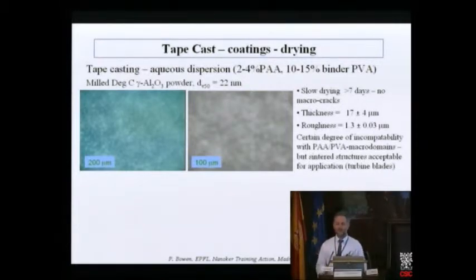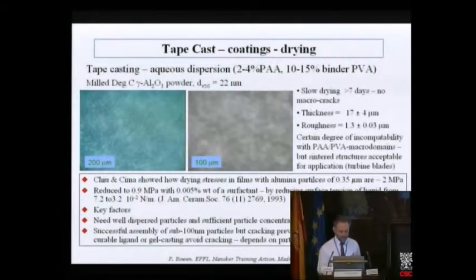We were trying to make coatings for turbine blade applications. The sintered microstructure of this ceramic coating afterwards was sufficient for the application. It worked. Whether or not the use and burning out of such a quantity of binder is economically viable for the application is a big discussion. So you can get there, but you have to add binders.